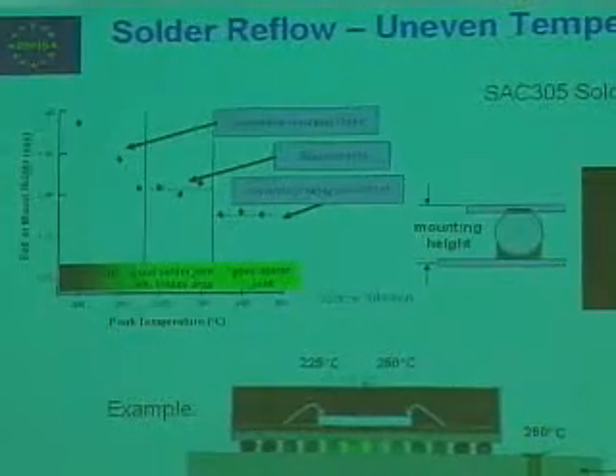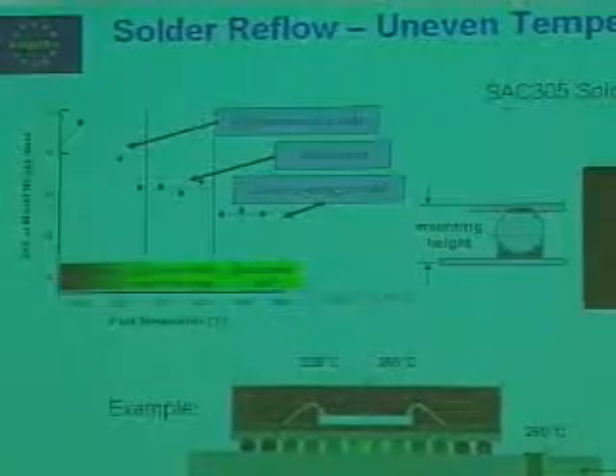And in fact, this is an experiment that was published last year where they actually embedded thermocouples in various parts of the package: at the chip, a solder ball in the center, a solder ball out at the corner or the edge, and then at a trace a little far removed. And you can see this was run in a reflow furnace that was set at 260, and out away from the package, indeed, they did see 260. 255 at the edge of the package, pretty close to 260. Everything's okay. Whoops, near the center of the package, it only got up to 240.